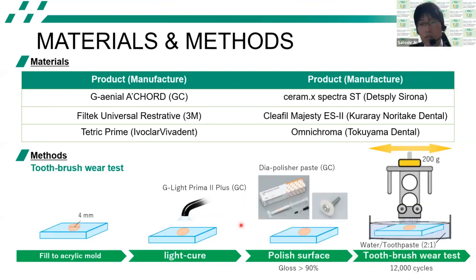Next, I show the toothbrush wear test method. Resin composite material was filled in an acrylic mold and light cured. The surface was polished with diamond paste to a gloss of more than 90%. Then it was brushed by a toothbrush with water and toothpaste. After 12,000 brush cycles, which is estimated to be 1 year of brushing, we measured the surface gloss.